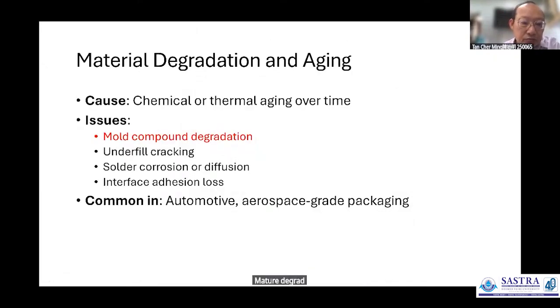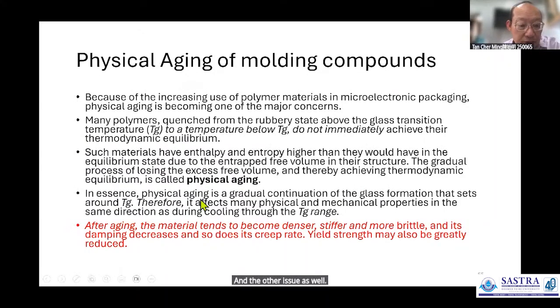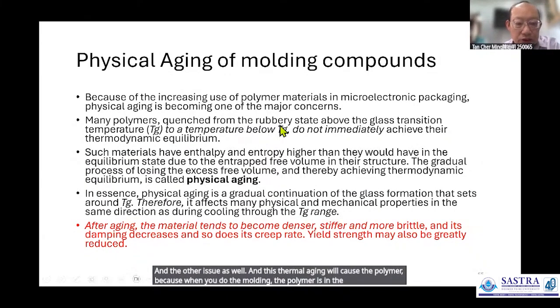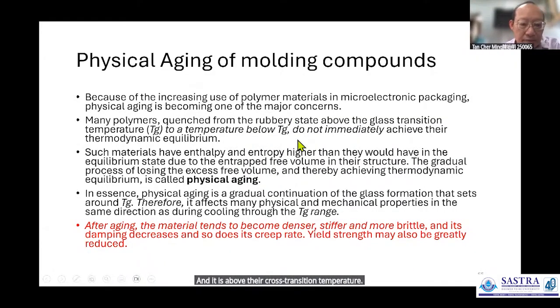Material degradation or thermal aging, as I said, the molding compound is a polymer, and they will keep on moving as you continue to operate. And there are other issues as well. This thermal aging will cause the polymer, because when you do the molding, the polymer is in the molten state, in the rubbery state, and it is above its glass transition temperature. Then you cool it down. As you cool it down, if you cool it too fast, there is no time for it to reach the thermodynamic equilibrium. So material always wants to go down to the thermodynamic equilibrium, and therefore they will start to move so as to reach the thermal equilibrium state.